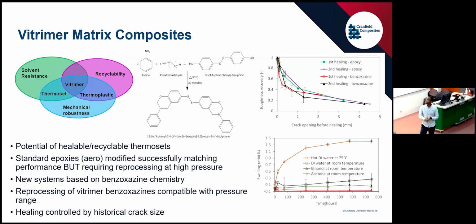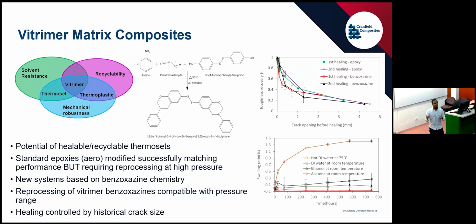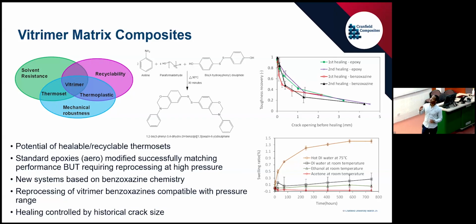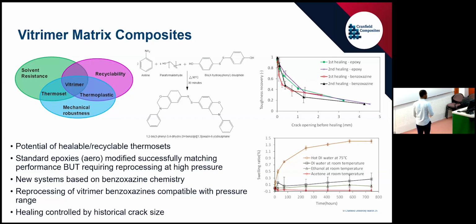So it still has the same high Tg, it still has the same high strength and stiffness that you would expect from a thermoset, but it can be reprocessed. And you can sort of tailor the chemical balance between the polymer precursors, to allow for a tailoring of that reprocessing temperature quite narrowly. So you can go from 160 reprocessing temperature down to the negatives, if that's what you so desire.